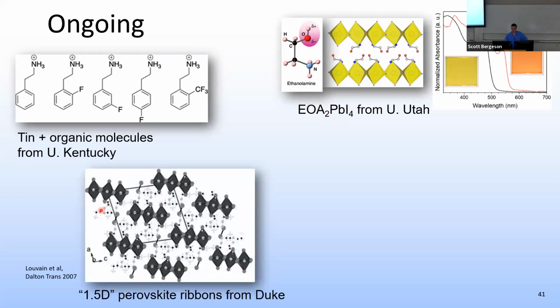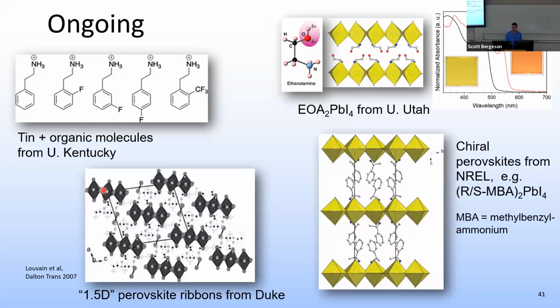We've also got some partners at Duke University that are making what we call 1.5 dimensional perovskite ribbons. So these ribbons extend into and out of the plane of the board there, and you can control the width of the ribbons. If you just have a single octahedron that extends into the board, that's like a wire. That would be a one-dimensional material. If you've got a plane of octahedra, it's a two-dimensional material, but here it's somewhere between a wire and a plane.